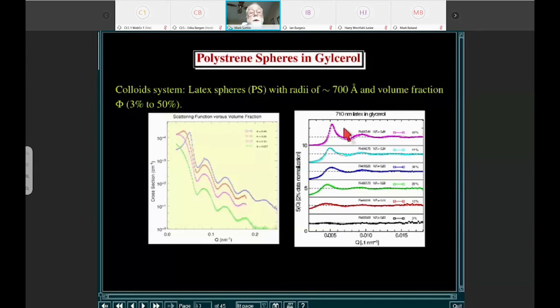The black line, which you can see going through all the data, is actually a fit to the Percus-Yevick line shape, which is basically the scattering of hard spheres. And you can see we've gone from basically 3% up to 49%, and you can see a build-up of the scattering of the structure factor where the particles begin to interact with each other.